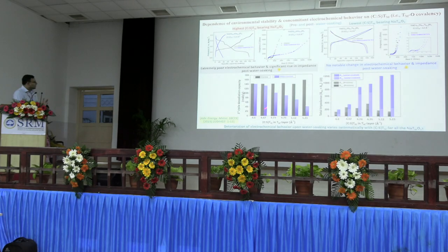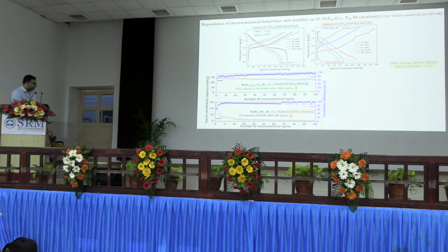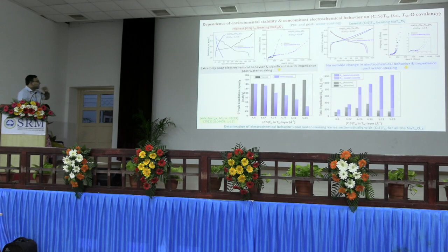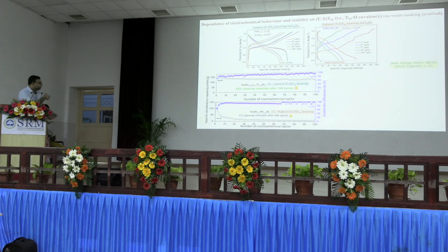And the materials with intermediate charge to size ratio follow suit when it comes to the capacity as well as the impedance. There is something more interesting in that, but I don't have much time to go through that right now. So anyway, this proves that if we lower the charge to size ratio of the cation combination in the transition metal layer, it can make the layered transition metal oxide highly water stable upon soaking even in water. Forget about living in air, it will be stable.